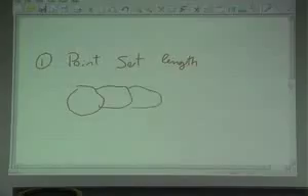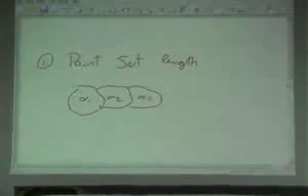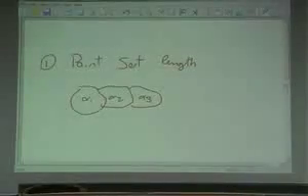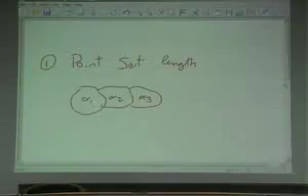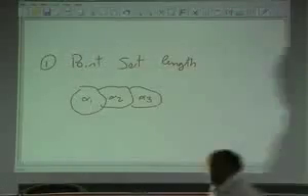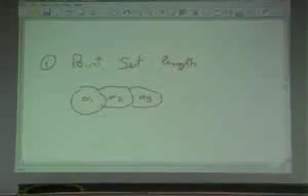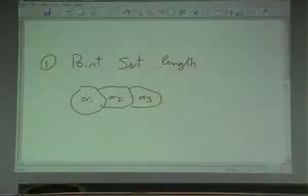The mosaic is this cartoon with alpha 1, alpha 2, alpha 3. We did this argument with the cavity. If the mosaic is correct, then in principle I can do the argument with the cavity in a simulation. I can take an equilibrium configuration of a liquid, take a small cavity, freeze all the particles outside the cavity, and redo the thermodynamics inside. For example, I do a Monte Carlo simulation just inside the cavity with a frozen boundary condition.